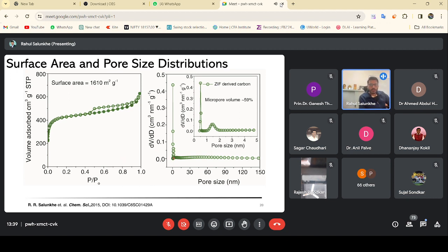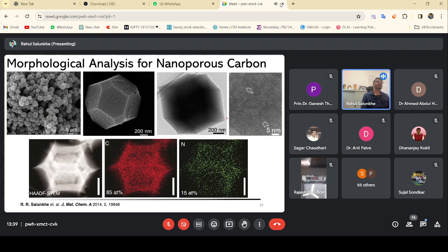We can see that they have a very good micropore structure, and if we look closely, most of the pores lie in the micropore range. The total micropore volume in this case is 59%. That means 59% of the pores are in the micropore region, and the other pores are in the mesoporous region. This is the typical morphology of our samples.